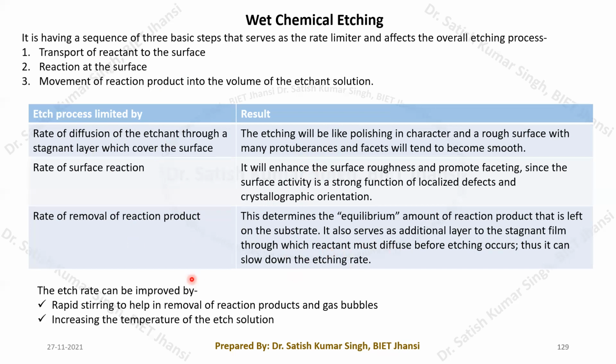Generally, rapid stirring of this solution helps in the removal of the reaction products and gas bubbles from the surface, and therefore your wafer is always exposed to a very fresh etchant solution, and then this reaction cannot be limited. It means that at that time your chemical will always be reaching your wafer surface, and this reaction will always take place.